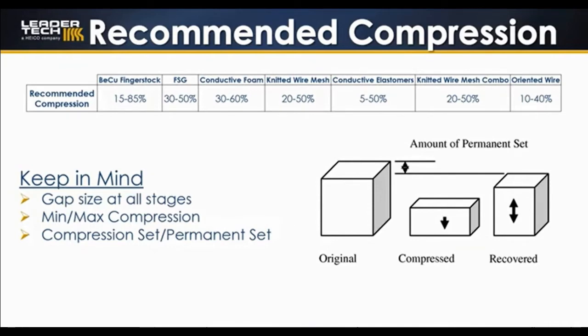In the case of conductive elastomers, the material is metal particles with a binder. Those metal particles can only contact one another with compression to create electrical contact. Over-compressing the material can also cause issues. The material can break, and over-compressing conductive elastomers can create separation between the metal particles and reduce conductivity.